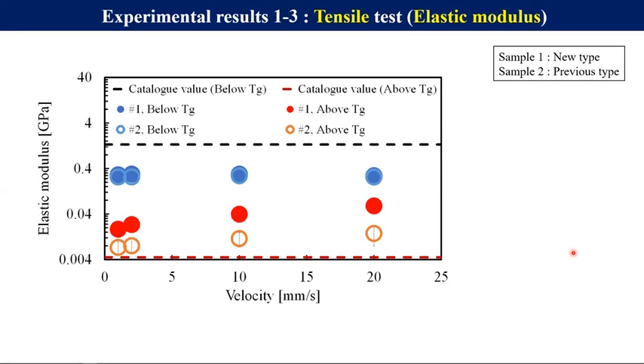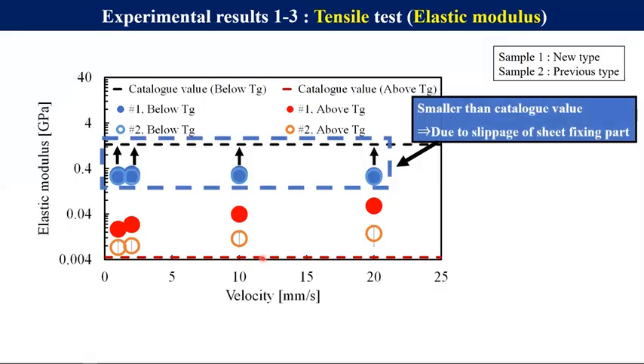This is the experimental result of the tensile test about tensile elastic modulus, and the vertical axis of this graph shows the elastic modulus, and the horizontal axis shows the velocity. I'd like to draw your attention to the tensile elastic modulus below TG first. Due to slippage of the sheet fixing part, the tensile elastic modulus was a bit smaller than the catalog value though. The results for each sheet were really close.